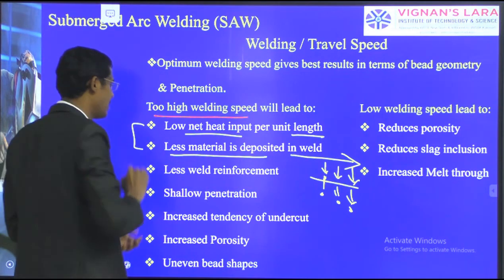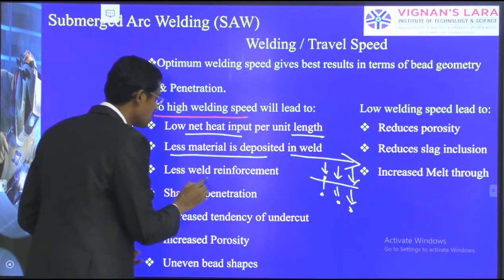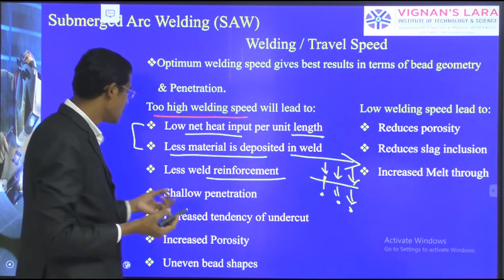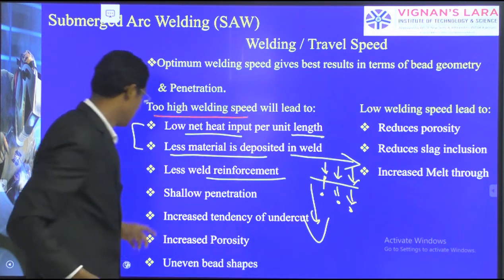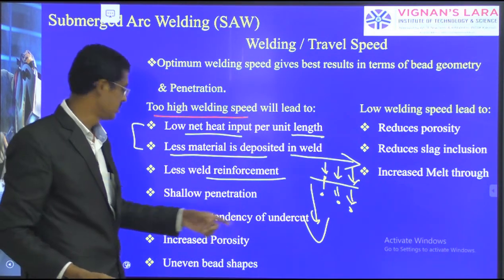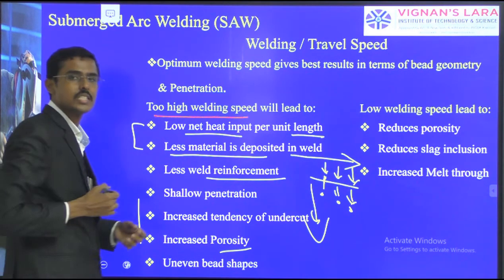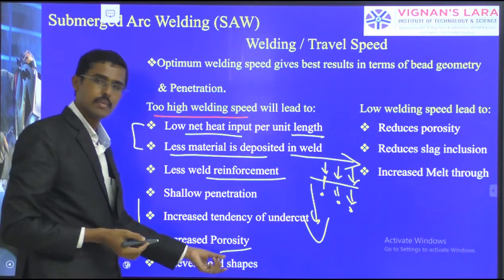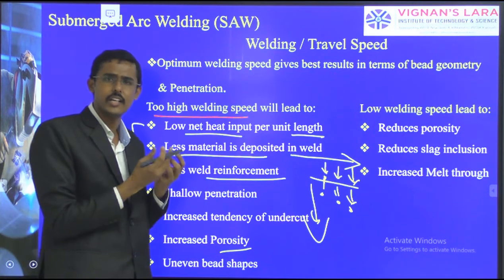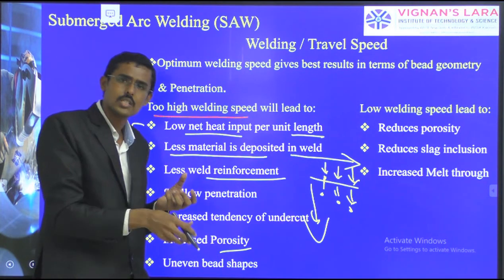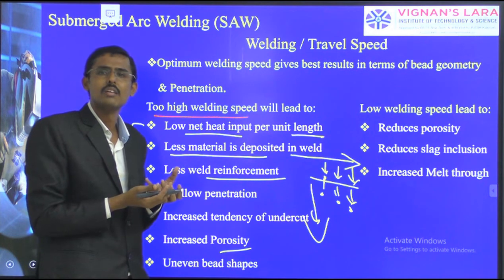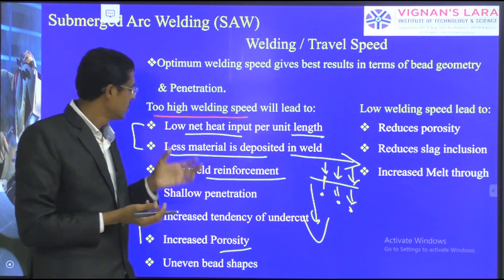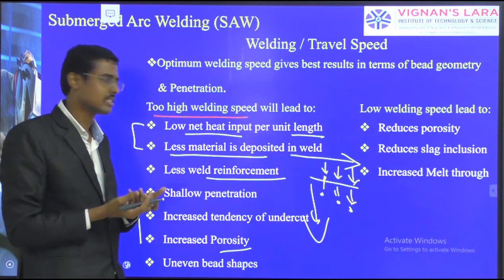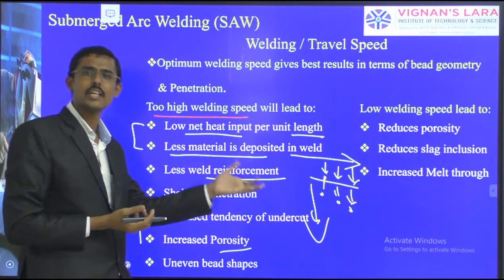See, these are interrelated. Less welding reinforcement, obviously less reinforcement will be there. Shallow penetration, deeper penetration will not happen. The tendency of undercuts increases, porosity increases. This all will happen when the travel speed is high. Uneven bead shapes. First of all, it should be heated. It is ready to melt, ready to deposit, that we are not permitting. If you are not permitting it to heat, the weld reinforcement will be less, penetration less, material melting less, all will